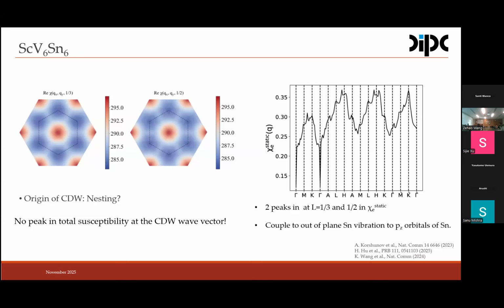We still need to understand why the phase transition is first order. It turns out that the symmetry of the low temperature phase allows for cubic terms in the free energy expansion. These cubic terms allow for a competition between the 1/2 and 1/3 propagation vectors of the charge order. And this competition drives the first order phase transition.